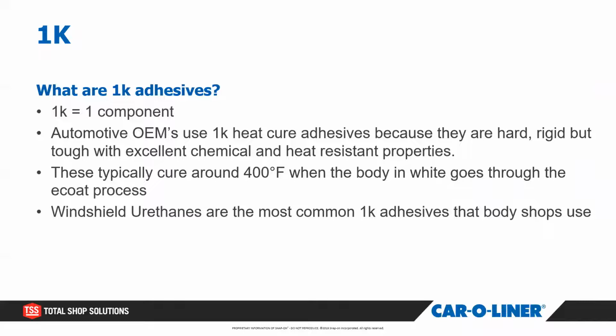Automotive OEMs currently, and it's happening more and more on every vehicle that's built, are using structural adhesive throughout the joints on vehicles, and they're using a 1K heat cure adhesive. And these are put into the joints when the car is being built. It doesn't actually cure until it goes through the paint shop and through the ovens to cure the paint. So a very high temperature, around 400 degrees. It can range from 350 to 450. Very, very high temperature.